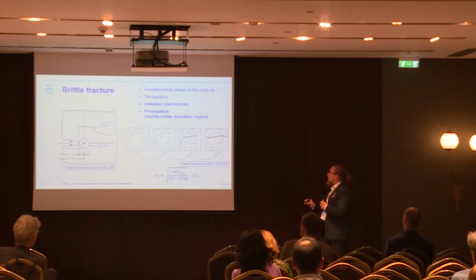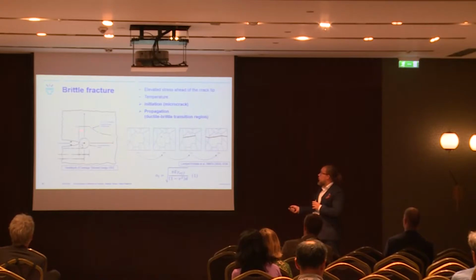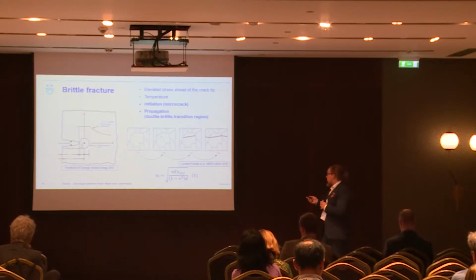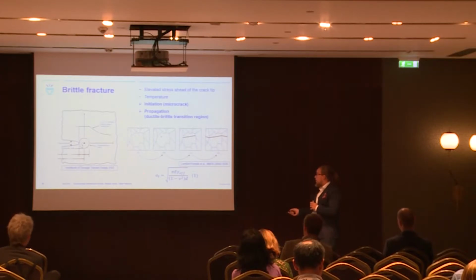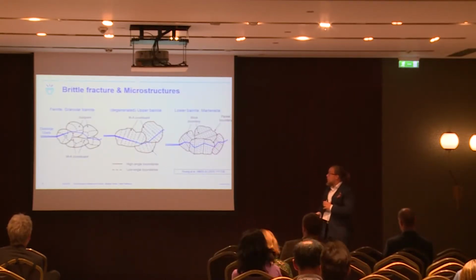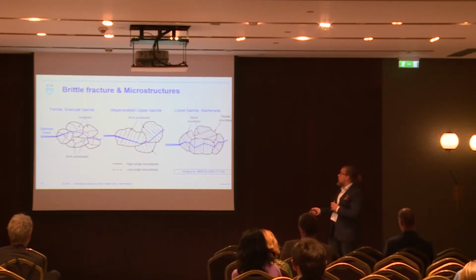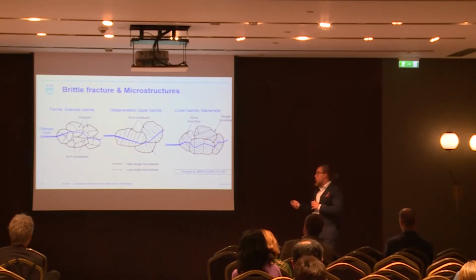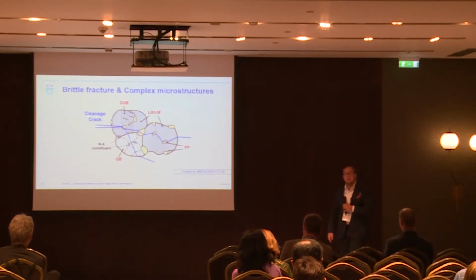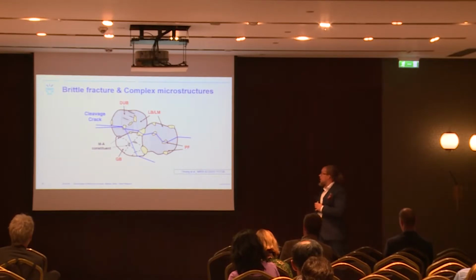We consider brittle fracture from the point of view of a local microcrack ahead of the macroscopic crack tip or a notch, depending on the specimen type, and the requirements for when this local microcrack propagates and causes the primary failure in these specimens. A popular way to assess this is the Griffith criterion. So, how does this go in different microstructures? In schematic cases, we have different sets of more and less effective boundaries that can either deflect or arrest the propagating crack. But in the realistic case of modern multi-phase steels, it can be a mess.